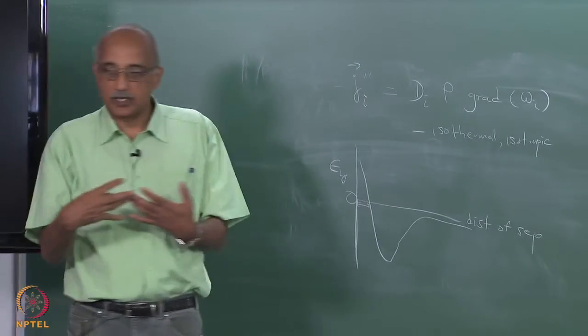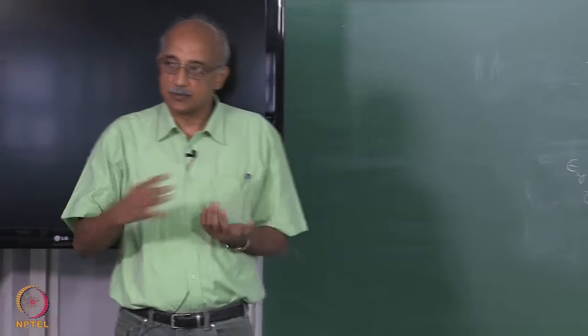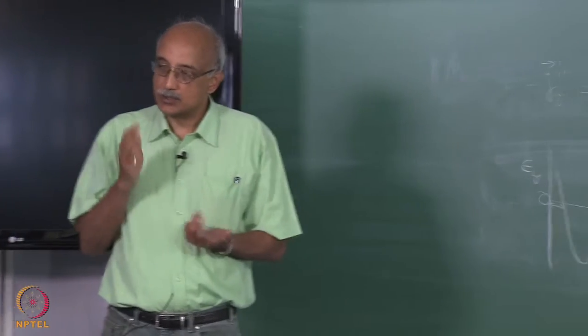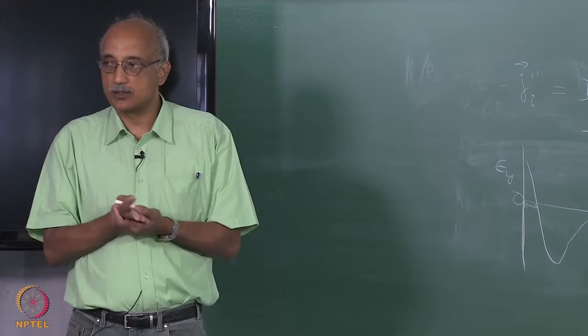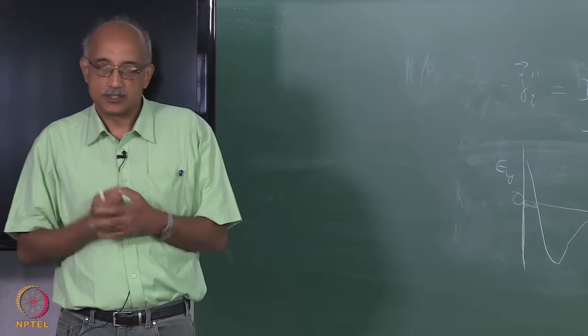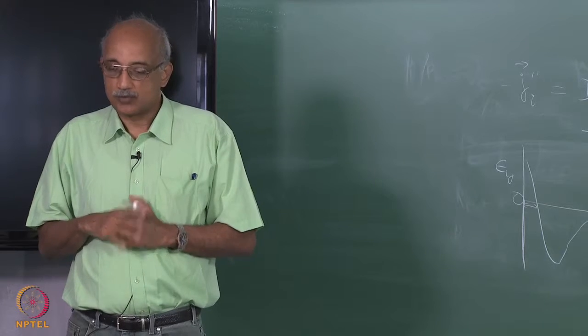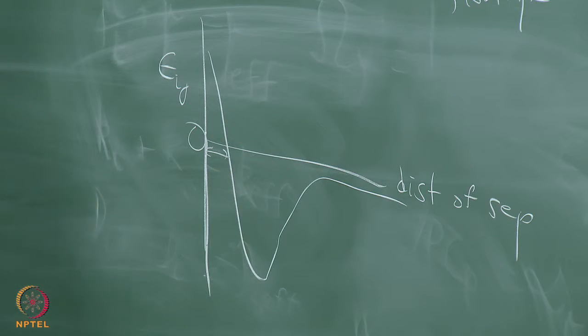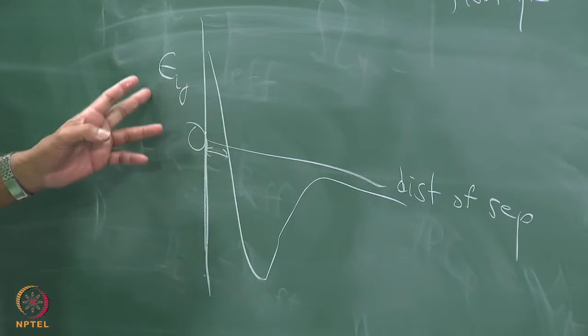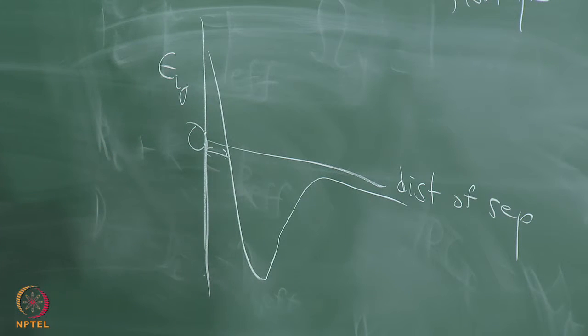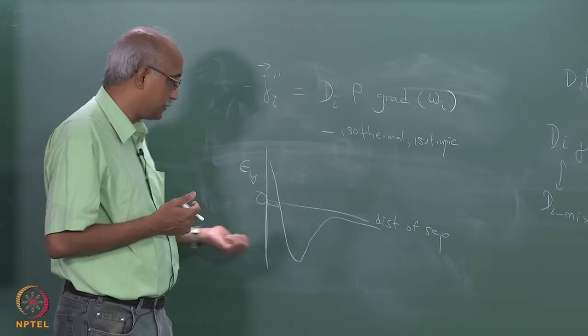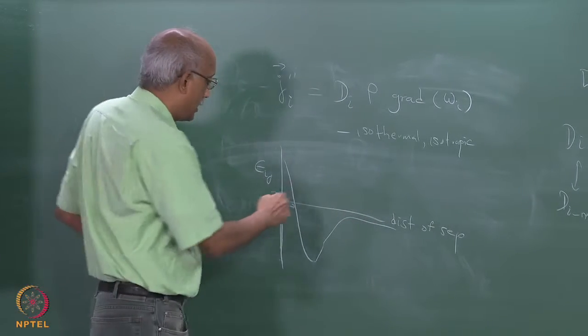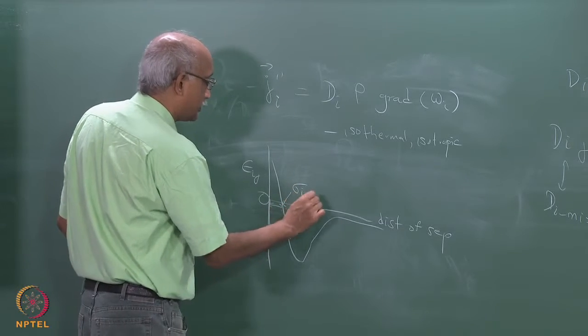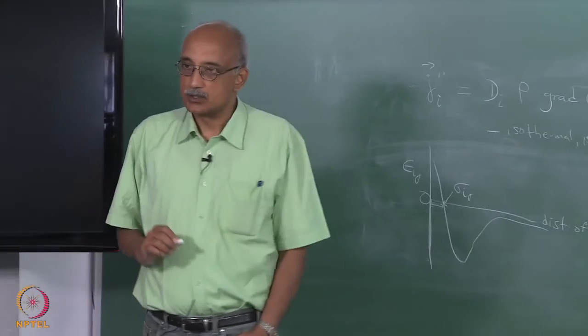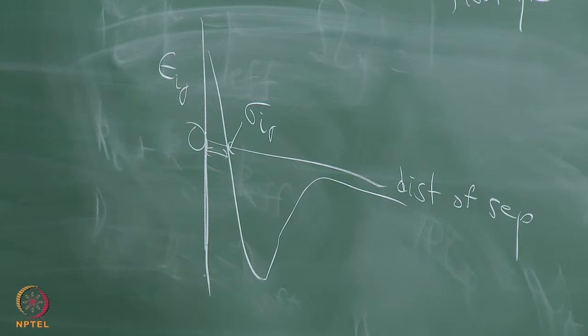So, as the molecules come very close together, there is a repulsive force. As they move farther away, there is an attractive force. So, there is a particular distance of separation between two molecules which results in a net force of 0, which is the equilibrium position of rest between these two molecules. So, that is essentially obtained by plotting the intermolecular potential between molecules i and j, which is epsilon_ij, as a function of distance of separation, and the distance at which it reaches 0 is what we call sigma_ij. So, it is the intermolecular distance of separation corresponding to the point where epsilon_ij equals 0.